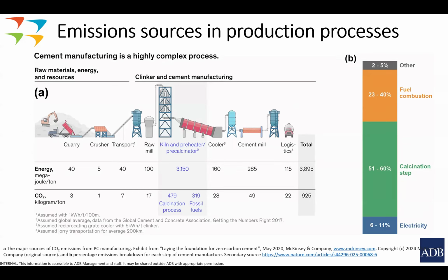Then you go to crushing, transport, raw mill, and the biggest contributor to emission and electricity is the kiln process and the calcinator. This is where the amount of energy used is the largest. Almost more than 70% of energy is going into the kiln, and it is also contributing more than 70% of the emission. So kiln, calcinator, and pre-calcinator are among the biggest contributors to emission. So our biggest attention when we want decarbonization will go to this place, followed later by the other processes, which are cement mill, cooler, logistics, etc.